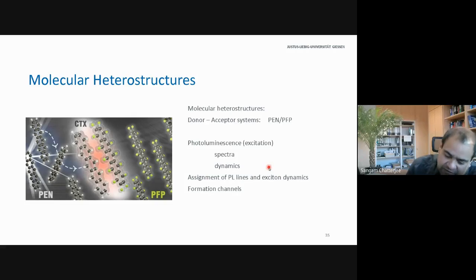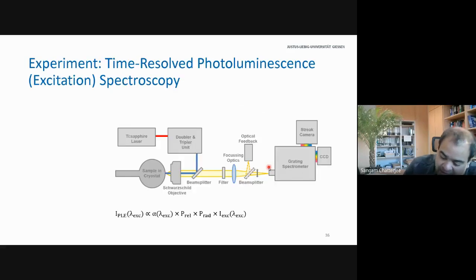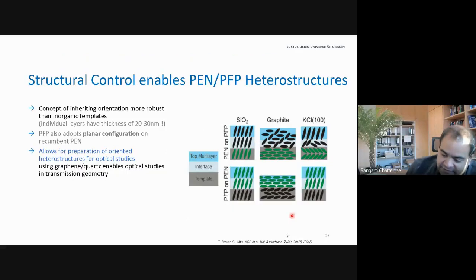It's typically not so easy to look at the oscillator strength, but look at the population. And therefore, we use time-resolved photoluminescence using a streak camera, which is probably the fastest camera that's around. The idea is it's basically like a cathode ray tube. It's a time-to-space conversion. Your photon excites an electron. Your electron gets streaked along your cathode ray tube, and you know by the point of detection which voltage the electron saw during its time of flight, and that way you can get very, very fast time resolution down to the picosecond level.